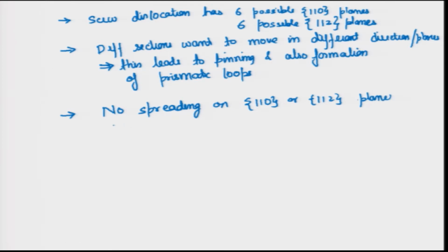If you remember, we had tau Pn, the Peierls-Nabarro stress, which is proportional to 2G over (1 minus nu) times exp(minus 2 pi w by b), where w was the spreading. So, the more the spreading, the smaller is the stress. If there is no spreading, it implies tau Pn is very large. So, this also implies that screw dislocations are not very mobile.